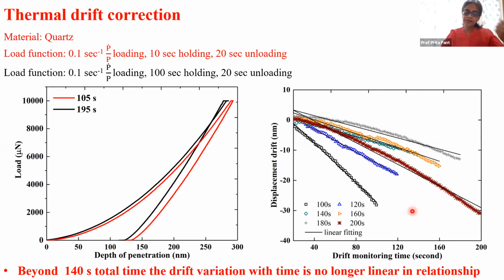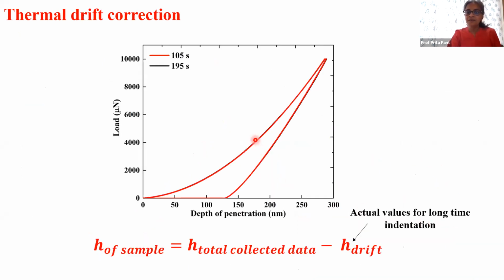So when Prakash had written in his earlier slide that his experiments were within this linear limit, we found that up to 140 seconds, it's still linear. So if your experiment, either you give a load function so that your experiment finishes in 140 seconds, in which case you're fine, or you basically do drift monitoring for the duration of your experiment. Just collect displacement data as a function of time, and then subtract that from your measured data. And if you do that, here are the red and the black curves again, the same data as the previous slide, and everything looks fine now.